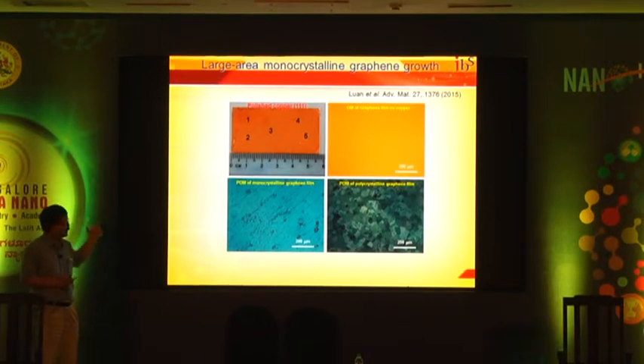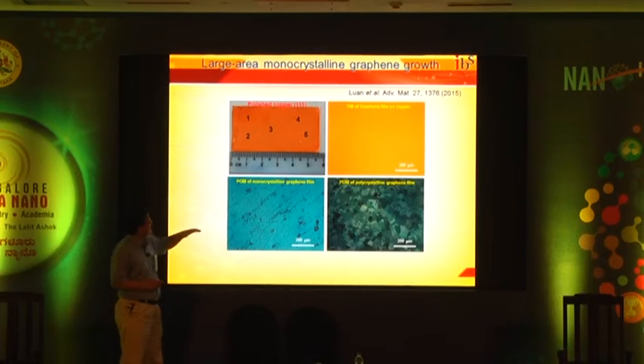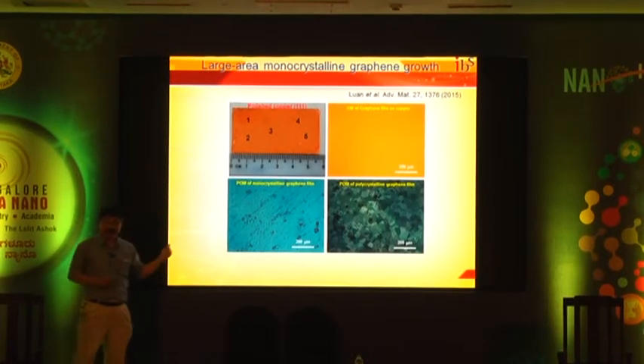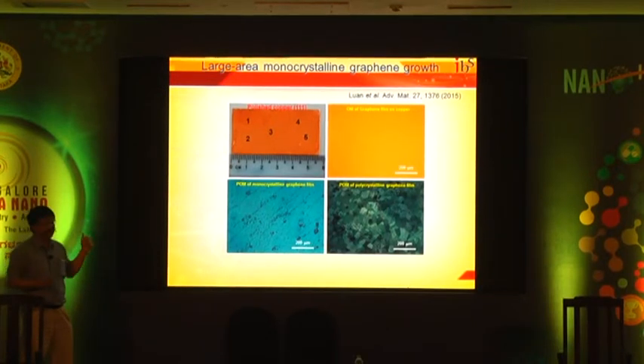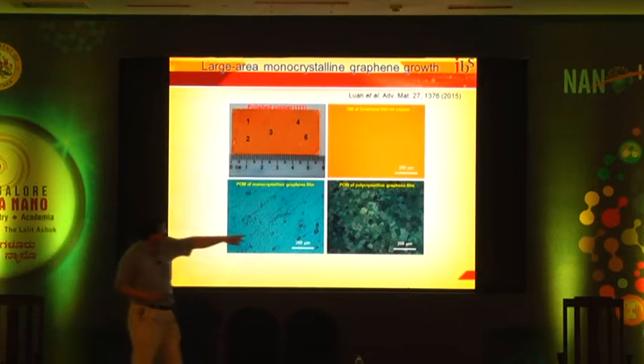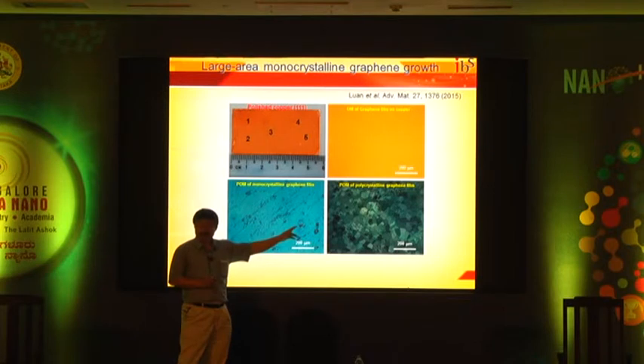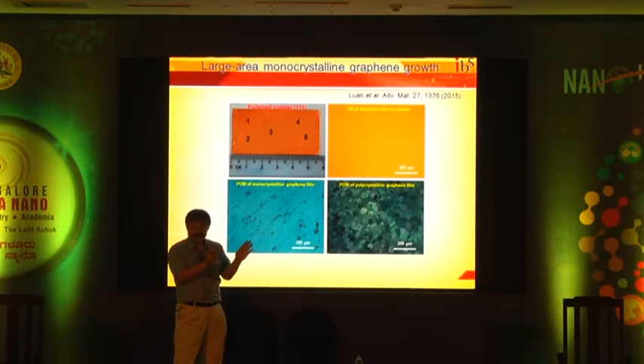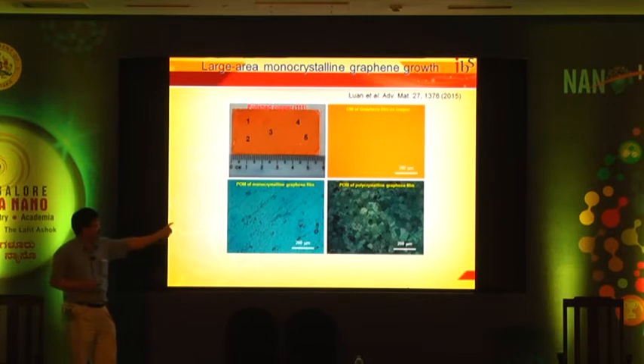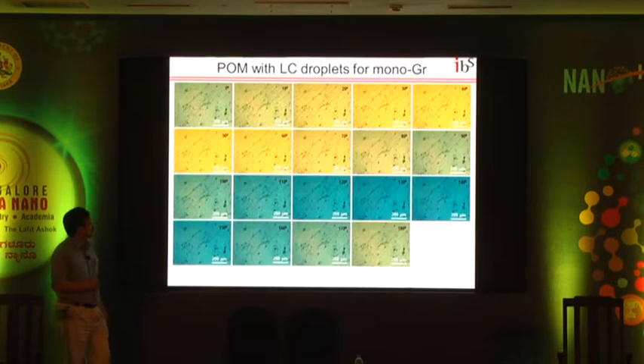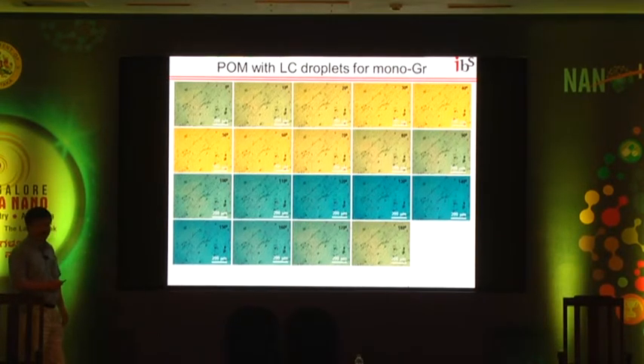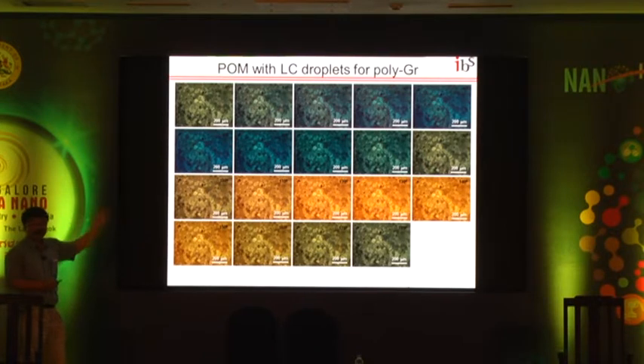When we follow this principle, here is another method of observing the grain boundary existence by using a liquid crystal droplet. You can simply drop the liquid crystal on the surface. And if you have a different orientation, the liquid crystal aligns in a different orientation. So you can actually see the different orientation. This is one good example, polycrystalline graphene. It shows different contrast. That means, because of different orientations of the liquid crystal on different orientations of graphene, you can see the difference. Whereas for the monocrystalline graphene, we don't see that. And for polycrystalline graphene, you can see there are different patches.